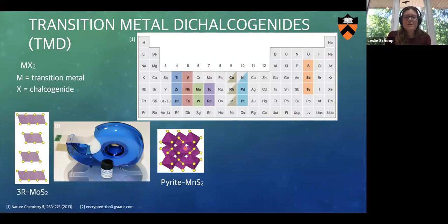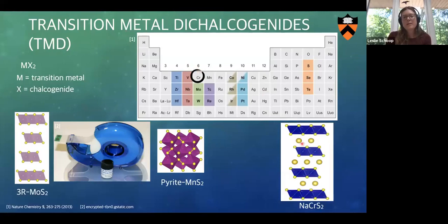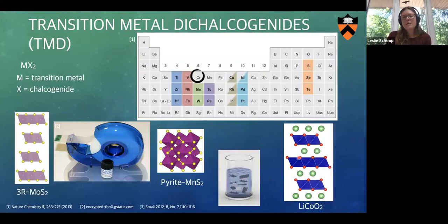So what we found interesting was that chromium, this material here, forms a structure like that, where you can use chemical exfoliation to delaminate it. And so it reminds you of this crystal structure of an oxide, where chemical exfoliation has been done successfully. The question is just, can we treat the oxide and a chalcogenide with the same chemistry and get the same results, or is there a difference? So that's my student Xiaoyu's work, who you all met earlier today.